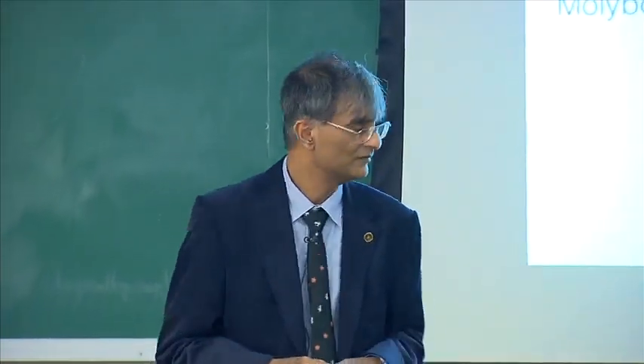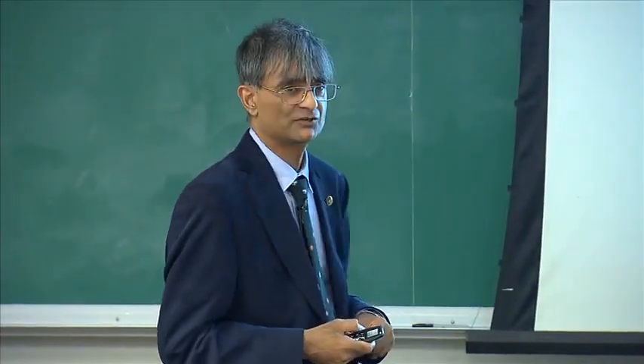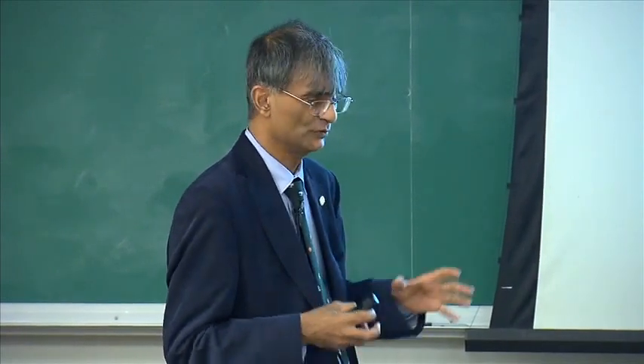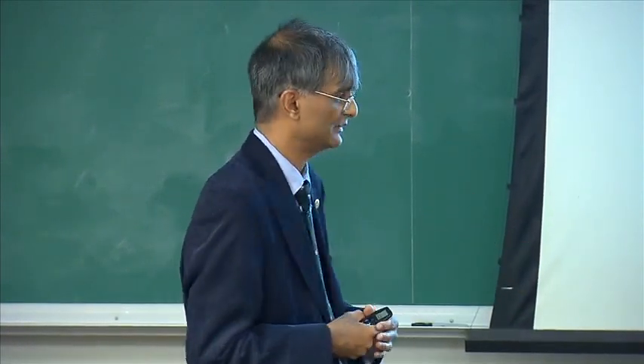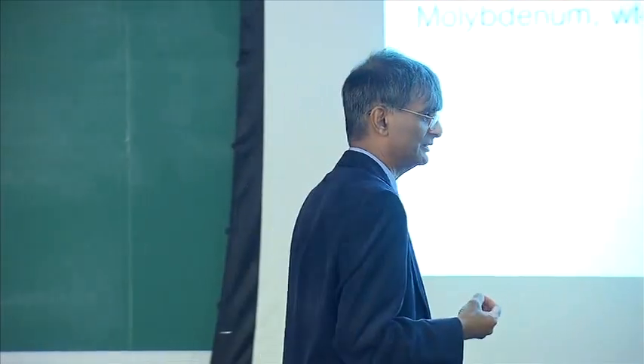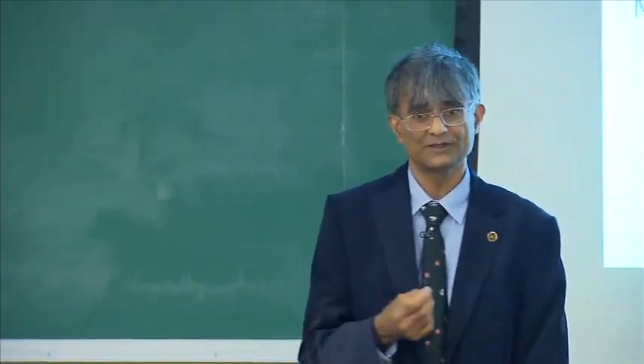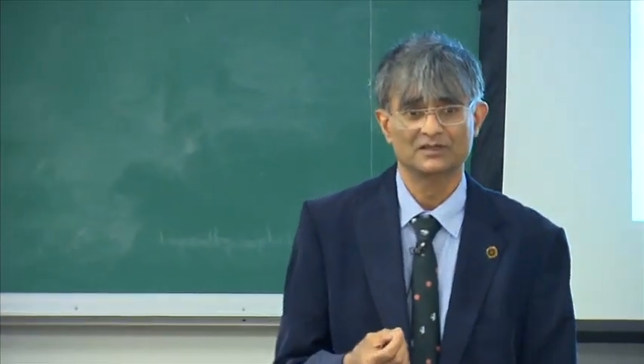and produced good experimental data. So we collected those data and created a neural network model asking the question that, look, I do not want a silicon concentration more than 0.5%, but I want the following properties. I want a certain amount of retained austenite and certain elongation and certain strength values. Find me a steel composition.